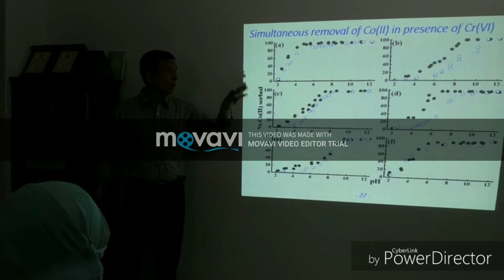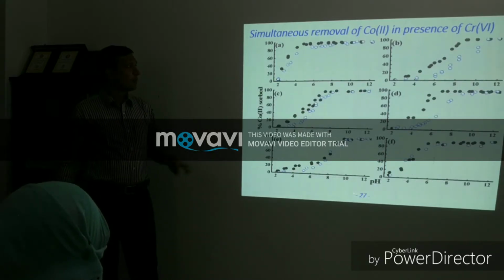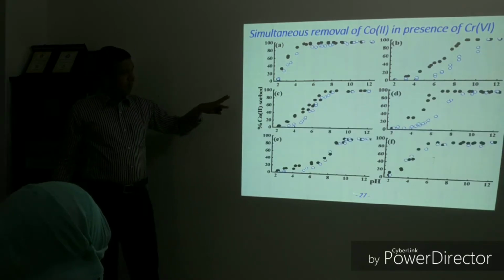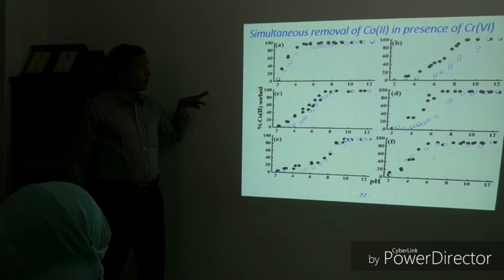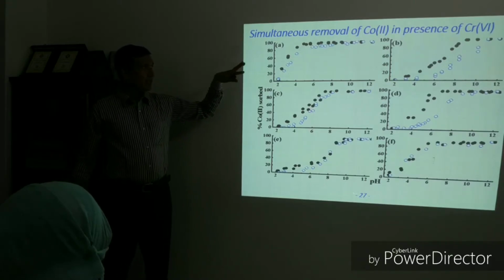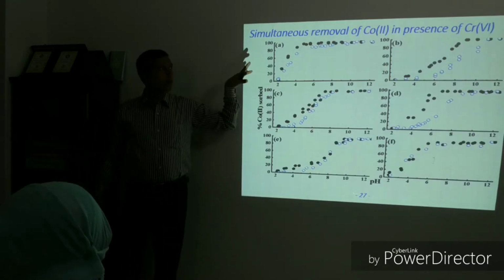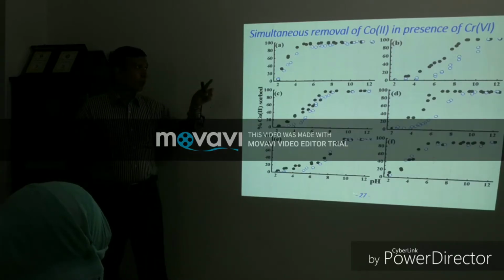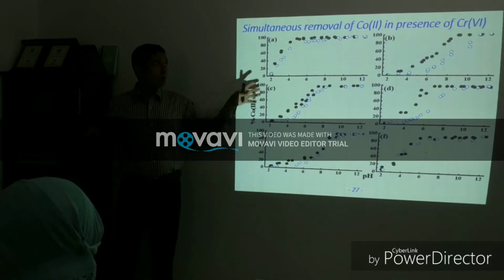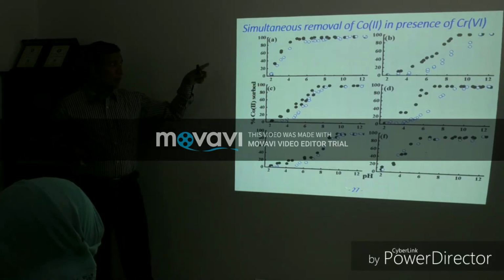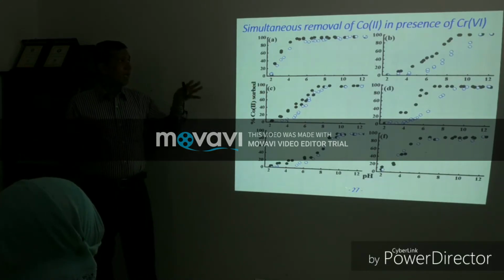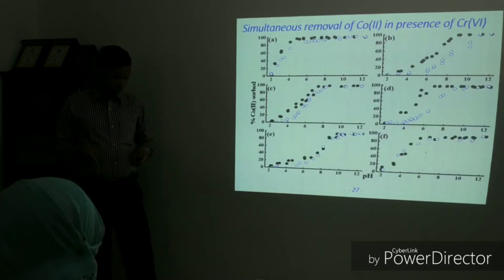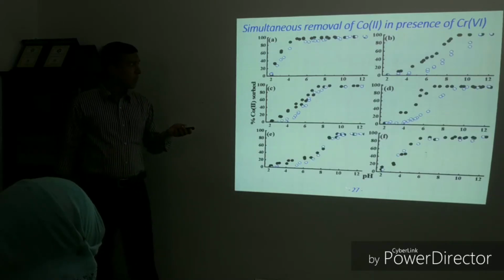Then we have studied simultaneous removal of cobalt in the presence of chromium. As mentioned earlier, in almost all cases, the presence of chromium decreased the amount of cobalt adsorbed. This could be due to the formation of solution complexes or competition between cobalt and chromium in solution for a finite number of surface sites.